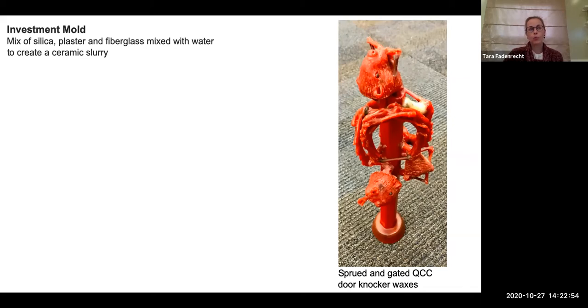fiberglass. When I talk about a refractory material, it's anything that's insulating, that's going to withstand the temperature of the molten metal being poured into the mold. We usually pour silicon bronze around 1100 degrees Celsius, and it also needs to withstand the pressure of that displaced air that's in the mold and then being displaced as the molten metal is poured in there. And of course, we want to keep it insulating, and that's why silica is so great about that, so that as the metal starts to solidify, it's kept protected and it can solidify at a gradual, progressive rate without too much shock to the material inside.